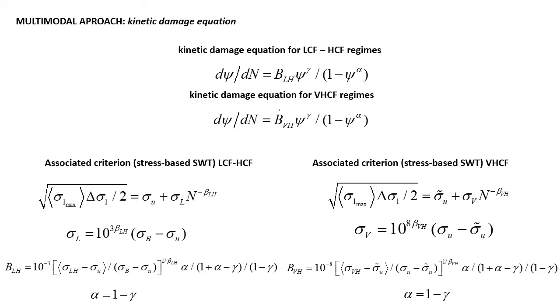The associated criterion for the function is presented below based on the SWT criterion. The parameters of the criterion, such as ultimate tensile strength and fatigue endurance in the low, high, and very high cycle fatigue ranges, are taken from the uniaxial tensile and fatigue tests.